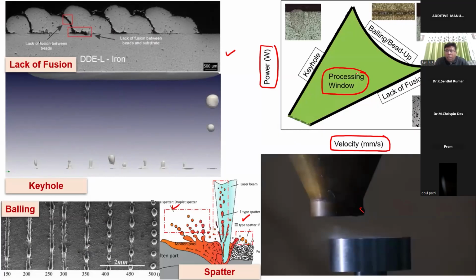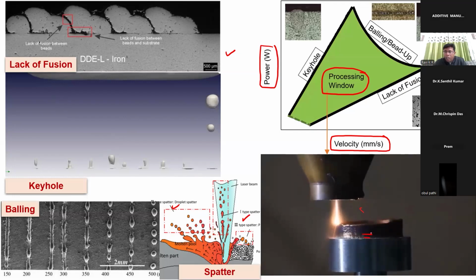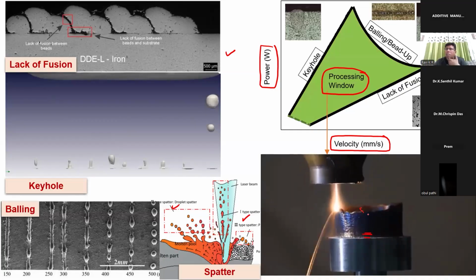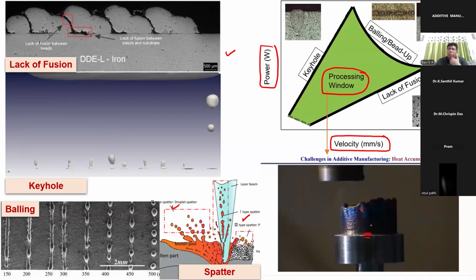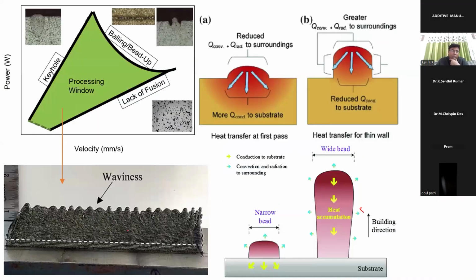This is how one would actually do parameter optimization, by doing trial and error. Let's say I have identified the optimum processing window, the optimum laser power and velocity, keeping the other parameters constant. Now I'm building with the optimum parameters. You see the first few layers work perfectly. Now the moment I get into a larger number of layers, I can see that the part is getting deformed. It is not actually printing as per my requirement. You see here that for the first few layers you get the parts properly.